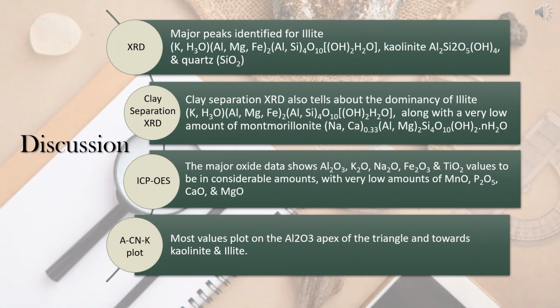The geochemical tests identified major peaks which correspond to illite, kaolinite, and quartz. On separating clay fraction from coarser particles and performing XRD, the dominance of clay mineral illite was again observed in the sample, with very low amount of montmorillonite.